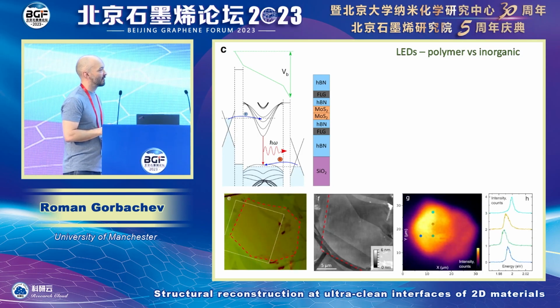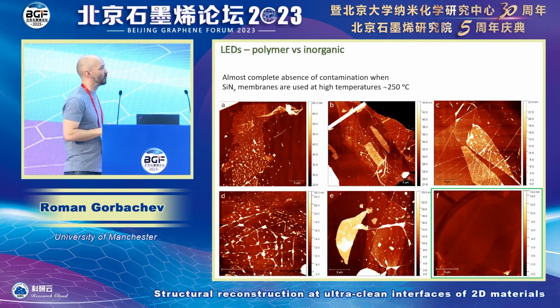And here you can see AFM of such a device. This one is about 25 or 30 micrometers. There is not a single contamination pocket. And the electroluminescence map looks extremely homogeneous compared to all previous works. And in fact, if you put it next to the polymer assembled, so these 5 are assembled with polymers with different types of stacking, different temperatures, and this one here is assembled with these cantilevers, and you can immediately see how much cleaner they are in terms of topography and the amount of interlayer contamination.